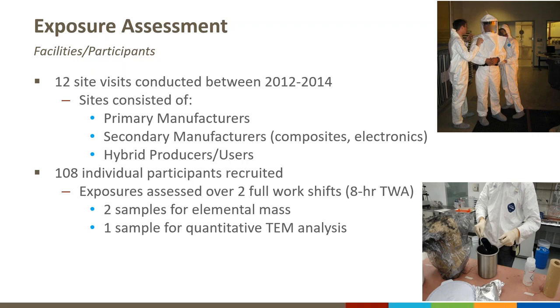So from those 108 individual participants that I previously mentioned, we assessed exposure over two full work shifts as 8-hour time-weighted average samples. For each personal sample, we collected three total samples. So two samples were collected for elemental mass, and one sample was for a quantitative TEM analysis. The reason why we wanted to collect at least two samples for each participant is because most of these facilities were operating more at what I would refer to as a research and development scale. So they weren't necessarily in industrial manufacturing at this point. So their tasks greatly varied from day to day.